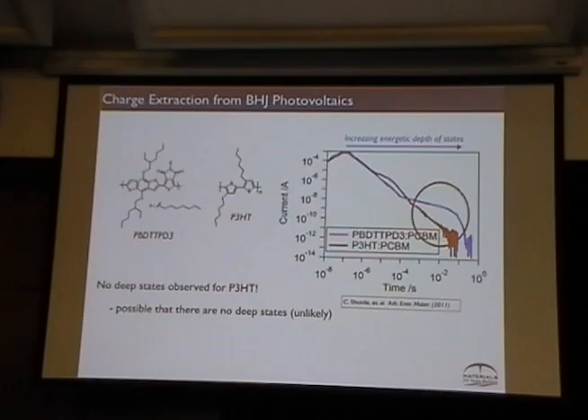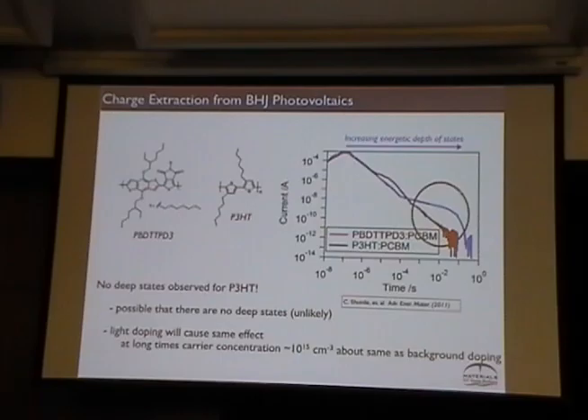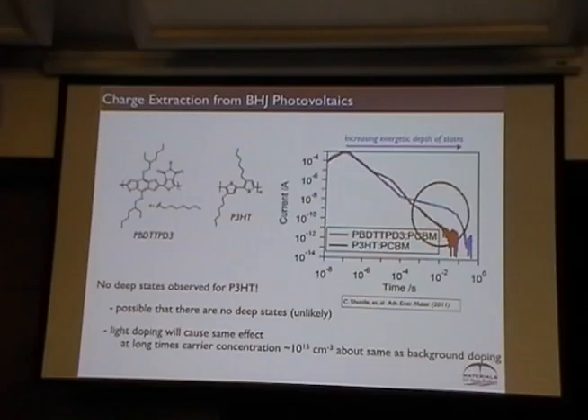Another possibility we prefer: P3HT is lightly doped. The charge concentration we're using here is something like 10^15 cm^-3. If you calculate the background doping for P3HT, it's easily that much. P3HT has a higher-lying HOMO level, while PBDTTPD has a deeper HOMO. Materials with a higher-lying HOMO tend to dope on their own if exposed to ambient — they have a higher background conductivity. Materials with a much deeper HOMO, for some reason, don't dope as much adventageously — the impurities in them are different. So if you have a lower-lying HOMO, it's going to be less conductive on its own.